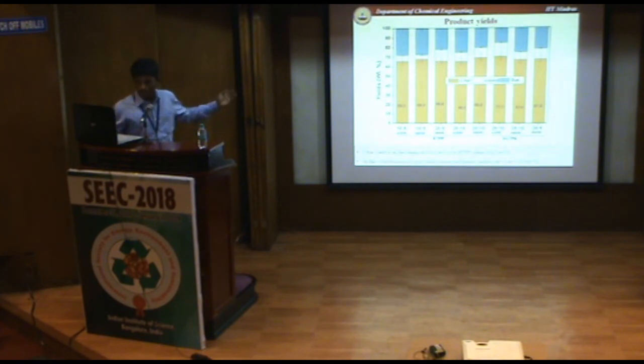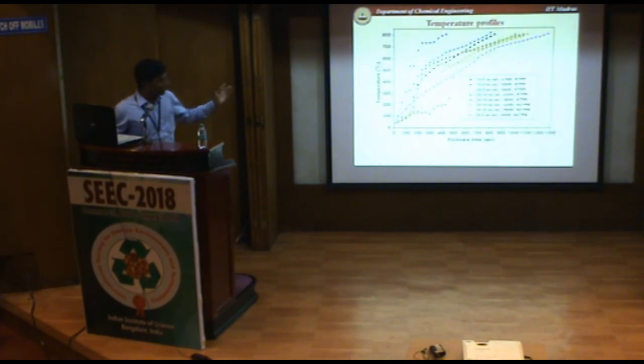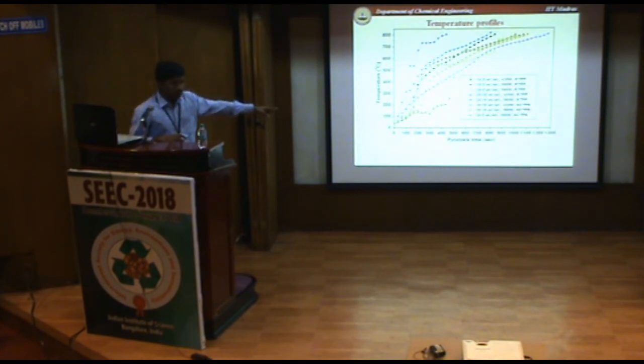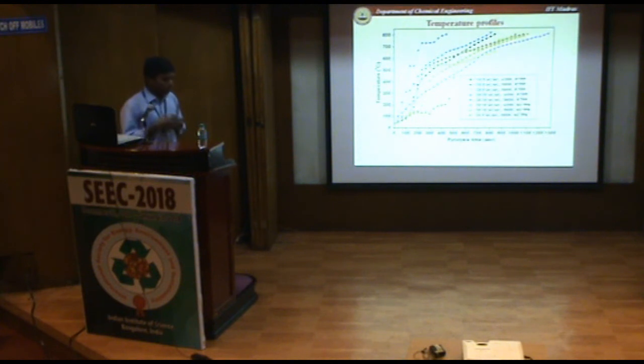So that's why we chose iron as susceptor to generate the nanostructures, and this is the temperature profile. In a microwave field, you can reach 800 degrees centigrade within 10 minutes. That is the advantage of the microwave, if you have the best susceptor, the best material which can absorb microwaves effectively. Everyone of us must have known that if you keep some 100 ml of water in a microwave and switch it on for 1 or 2 minutes, it gets boiled. That is the efficiency of microwave heating.